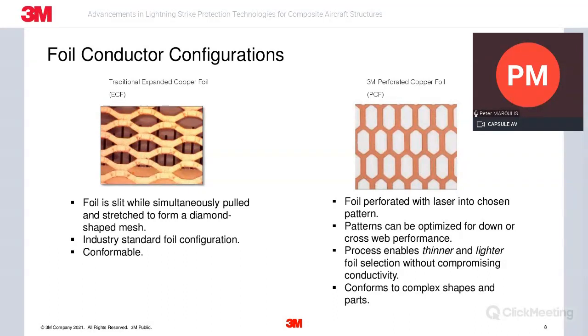In this slide, I want to expand on the differences between the expanded copper foils and the perforated copper foils. In terms of the expanded copper foils, the foil itself is cut. So there's a slit, as you could see on the image on the left, and then it's stretched. So what you end up with is those nodes that you see in between those open areas. If you look at the cross section of the wires, when you look at the nodes, you have a large amount of copper there, which is essentially not doing much in terms of electrical performance. Theoretically, you need a constant cross section throughout the entire network. There's a lot of excess copper in these nodes.